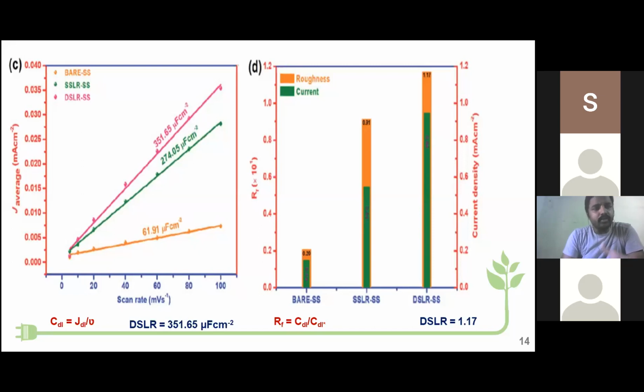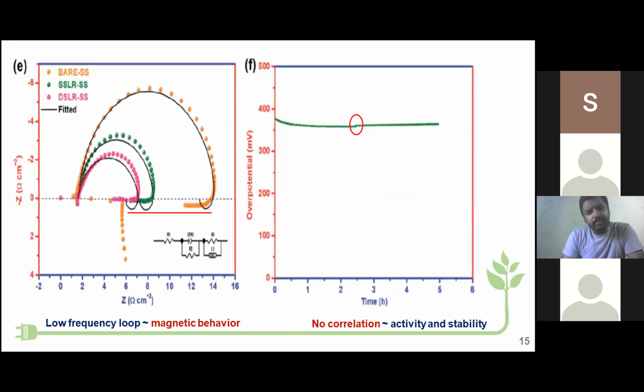Figure E shows the electrochemical impedance spectroscopy of the as-fabricated electrodes. It is clearly seen that the Nyquist loop or semicircle is large for the bare stainless steel, whereas for single side it is reduced, and for double side it is further reduced. So once the semicircle is reduced, it implies that the charge transfer resistance is reducing, and simultaneously the double layer capacitance or conductivity is increasing.